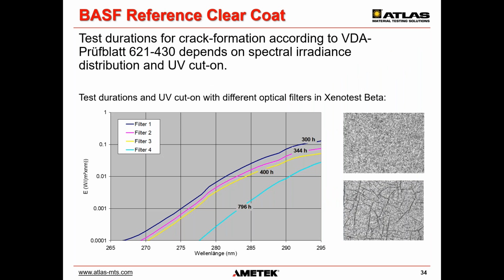This is from a study where the BASF reference clear coat was used in a xenon instrument to assess differences in UV cut-on. What the researchers did, they used different UV cut-on filters and researched the crack formation. And the crack formation appeared at different times using the same moisture cycle for the different cut-on filters, 1, 2, 3, and 4. When filters with a short UV cut-on were employed, the cracking appeared rather quickly, whereas it took longer for cracking to form when longer wavelength UV filters were employed. Maybe trivial, but in practice, this is sometimes not taken seriously enough.